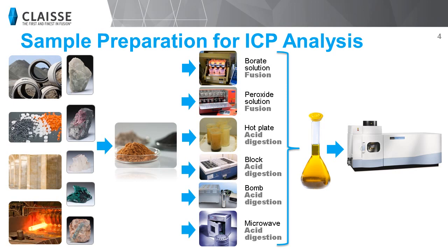There are also many ways to prepare your sample for ICP analysis. Let's divide them in 2 categories. The first category is acid digestion, that includes hot plate acid digestion, block digestion, acid bomb, and finally microwave. These techniques use strong acids like nitric acid, aqua regia, and even hydrofluoric acid. The second category is sample preparation by fusion, either lithium borate fusion or peroxide fusion. These techniques allow you to dissolve metals and other non-oxide samples quickly and rapidly. You can then get rocks, catalysts, ceramics, lime products, and many more in solution without HF or other strong acids.